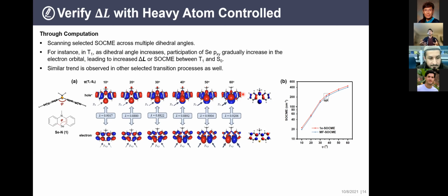So it's very easy to achieve this through computation. We basically fix the molecular structure while we fix the bending angle during the computation and do the geometry optimization. And as expected, we saw that from 10 to 60 degree bending angle, we have a much larger increased spin-orbit coupling value. But how to realize this in experiment?